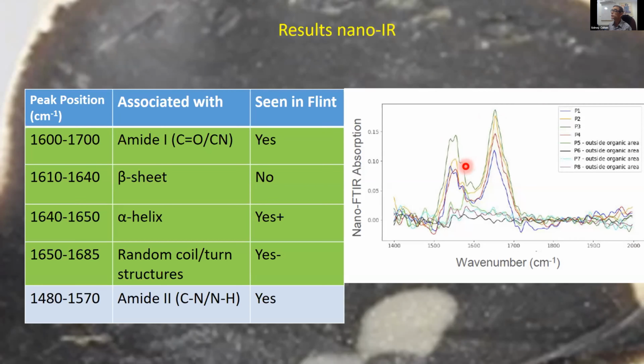What we see here are the amide 1 and the amide 2 peaks, which are very, very prominent in those organic micropools. If we look outside in the flint, then you don't see them at all. You only see them within those organic micropools. The results are tabulated here to the side. We see both the amide 1 and the amide 2 peaks. The amide 1 can be broken down into its structural components, whether it represents structurally a beta sheet or alpha helix or random coils. And as you can see, we really did not see anything which could be corresponding to beta sheet, but we did see something which looked like the alpha helix and some random coil. This is shown in these mappings.